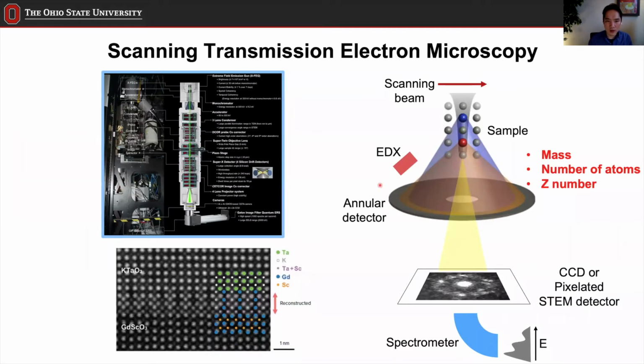Okay, so a little bit of background on our technique. It's scanning transmission electron microscopy. Transmission here means that our electron beam is penetrating through the sample, and then we get the signal, and we analyze the signal to get the atomic scale information. Some of you may be familiar with just transmission electron microscopy, and this is not the same. When you have just TEM, that usually means you're using the electron plane wave. In that case, it is very similar to what you are used to in optical microscopy. It's just that you replace the visible light with an electron wave, and that becomes essentially transmission electron microscopy.